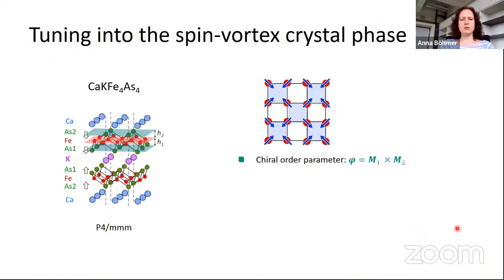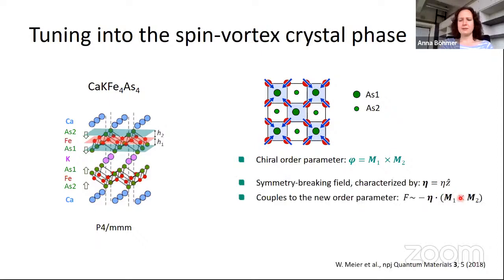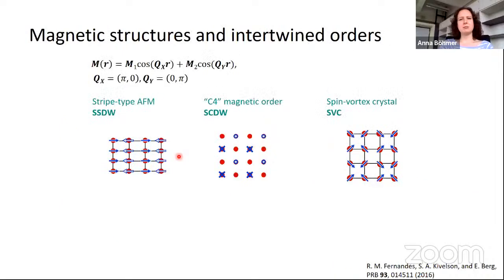There's a reason why we find exactly this complicated structure in exactly this material, and it has to do with my intertwined order, with these two amplitudes, two order parameters, and the vector product. Maybe, well, it's a structural reason. It has to do with these alternating layers. So we understood why likely we got this. We are not sure, but we understand why it's more likely to get this option 3 magnetic phase in this material. And with this, I would like to summarize.